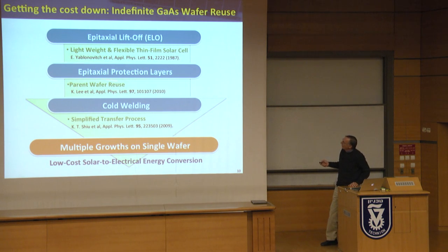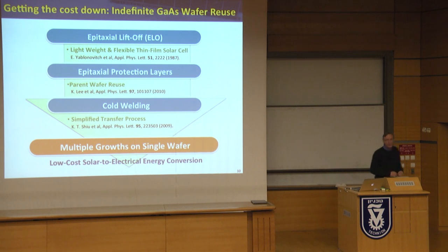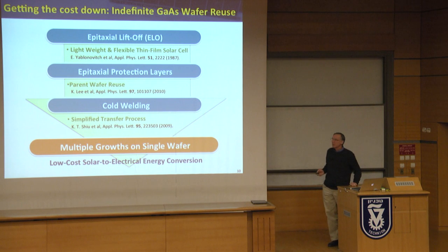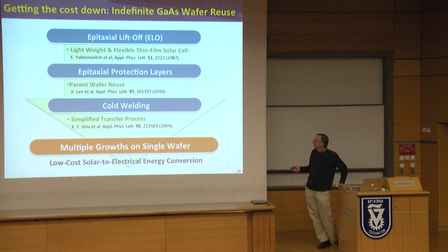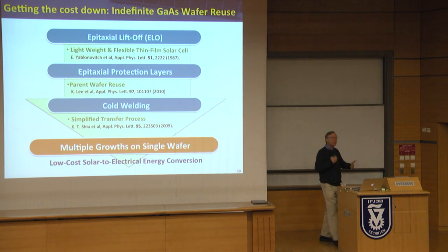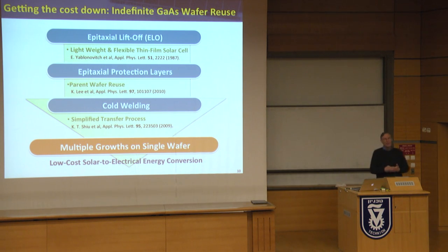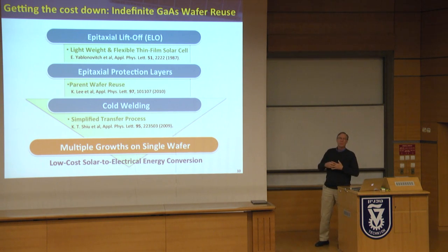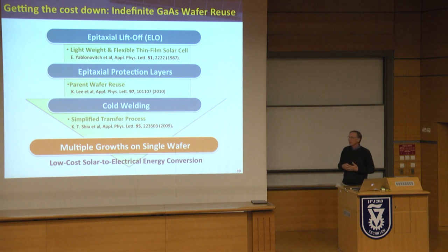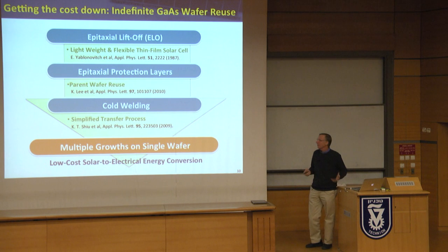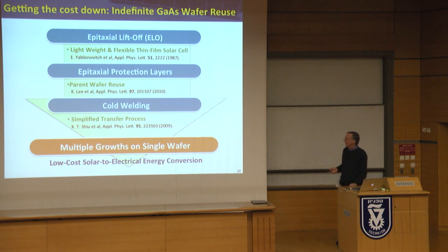We came up with, or my students came up with not long ago, this concept of epitaxial protection layers that allowed the wafer to remain in its pristine state after you peeled off the material. Further, we never use any glues. We just cold weld, and I'll talk about that, the epi to a plastic substrate without any adhesive. So it's extremely flexible and very cheap and extremely lightweight. Adhesives tend to crack and be bulky and heavy.